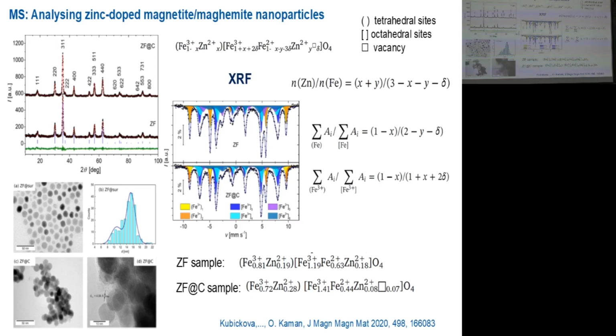So, if you formulate such a general description, you have there 3 variables, x, y, and delta. So we need 3 equations to resolve this situation. And as I mentioned, you will measure XRF to determine exactly the ratio of zinc and iron. So this is your first equation. And you can measure Mössbauer spectra, and you can quantify the amount of iron in tetrahedral sites, the amount of iron in octahedral sites. You can express it as a ratio and assemble this equation based on the formula. And similarly, you can quantify the amount of iron 3 plus and amount of